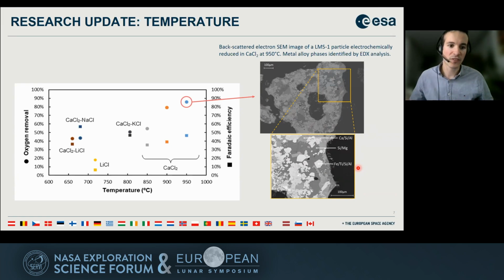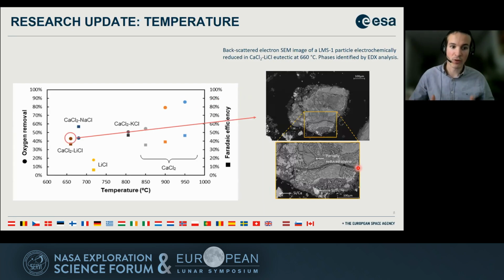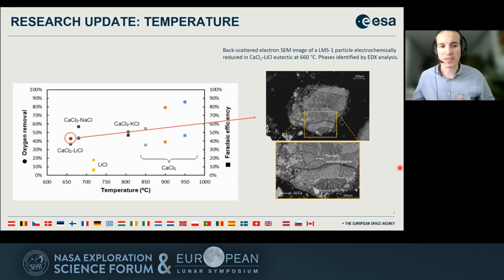The problem comes more when we have a lower reduction. Even at 40 to 50%, it's much harder to distinguish what exactly happened to the material, as the oxygen extracted probably comes from a bit of every mineral, but not to the point that you can actually distinguish metal phases. Here by EDX, we could distinguish maybe a partially reduced olivine, some metal phases, but only in very small pockets of silicon calcium or silicon titanium iron. This is just an example, but we had the same with the other partial reductions. It's really hard to follow exactly which mineral we use first and what the different steps are. So we maybe need to try single minerals and see what happens to them to understand exactly what the reduction process is at the mineral level.